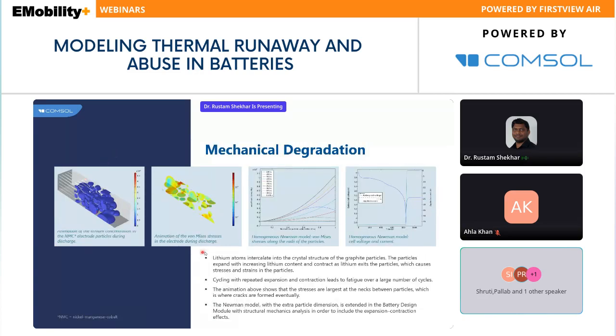In mechanical degradation, what we observe is that, let's say your lithium intercalation is happening in this particular domain. So these particles will face some kind of stresses which we can visualize here, and based on the intercalation, the crystal structure of the graphite particle will change. And so we will make a 1D Newman's model or a 3D detailed model, and we can extend this battery model for structural mechanics and see, because of expansion and contraction, how the battery will perform. Then we can compare at different times and at different locations how much stress is getting generated.